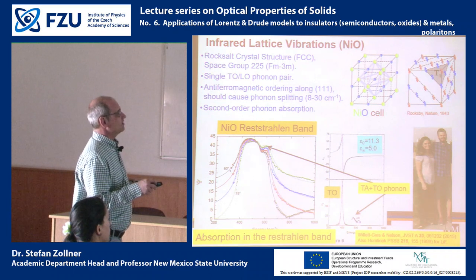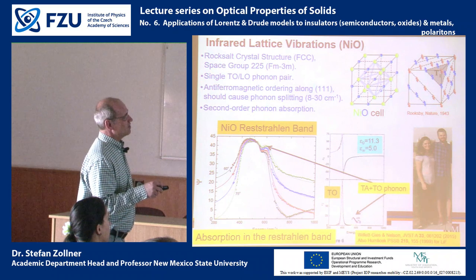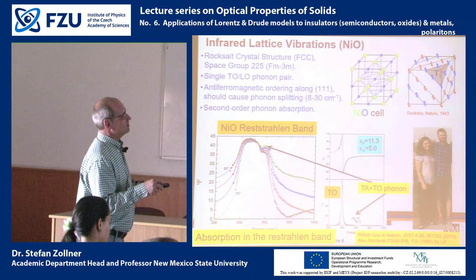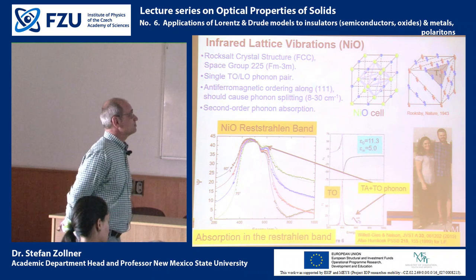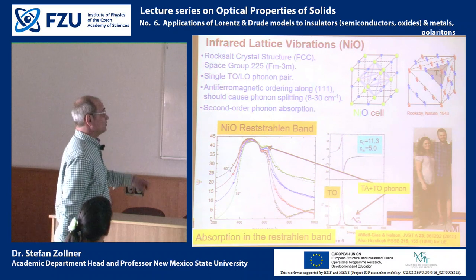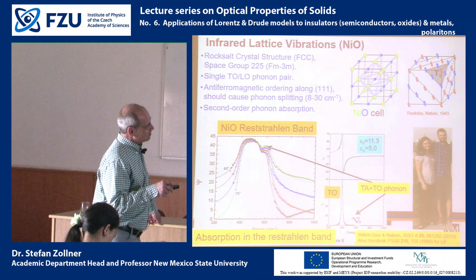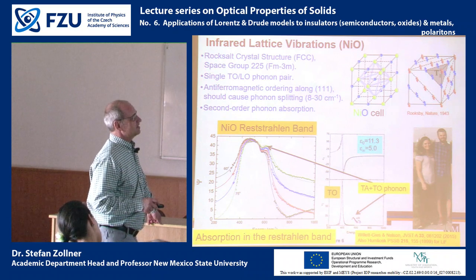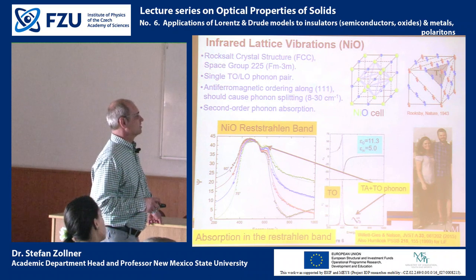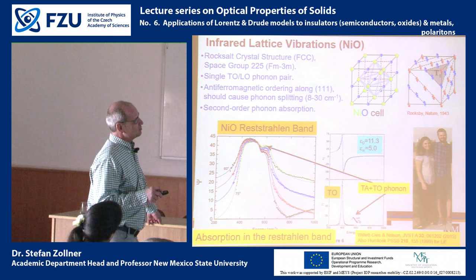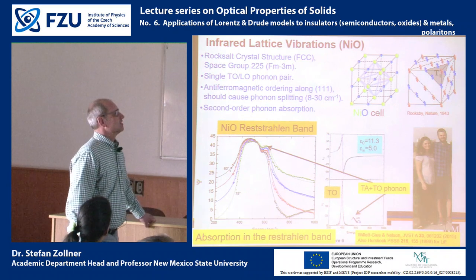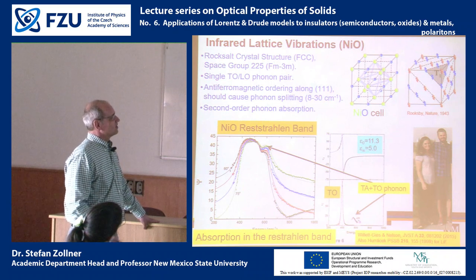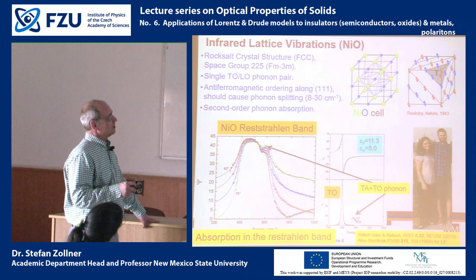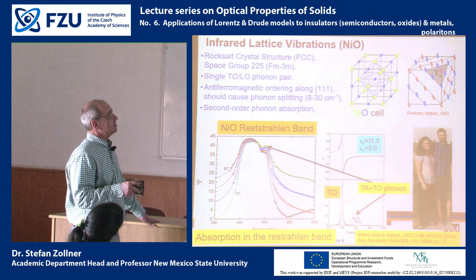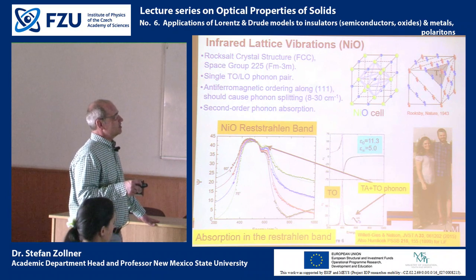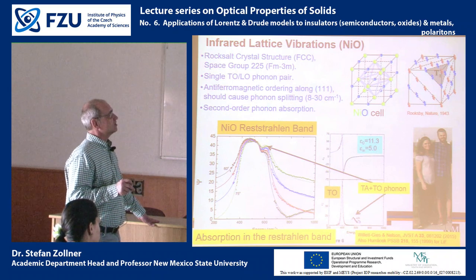And if we look very carefully at the absorption coefficient, and we multiply this here by 20, then we see, yes, there is another peak. At first, I thought that this peak was due to the antiferromagnetic ordering in nickel oxide. But unfortunately, as Humlicek points out, we see the same peak in lithium fluoride, which is clearly not antiferromagnetic. And we also see the same type of terrace. So this peak is actually not coming from the antiferromagnetic ordering, but from two-phonon absorption.